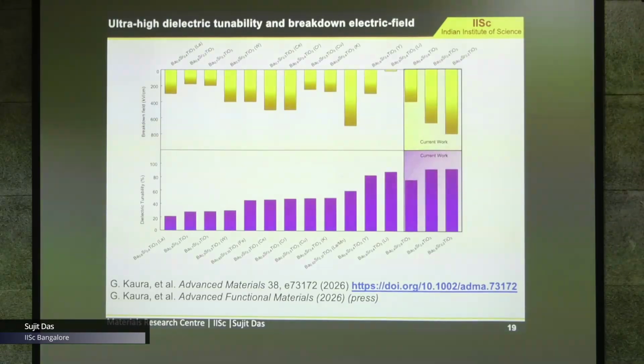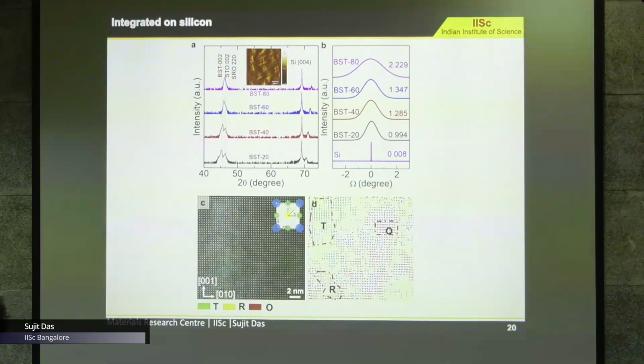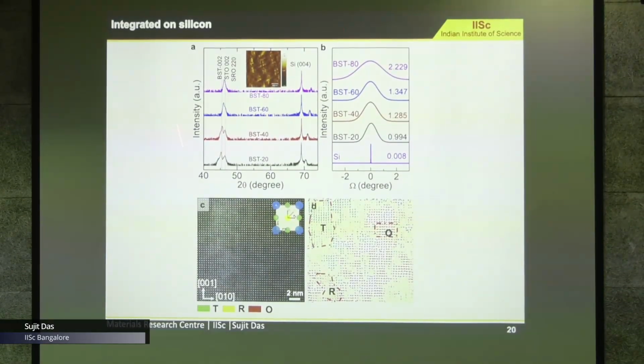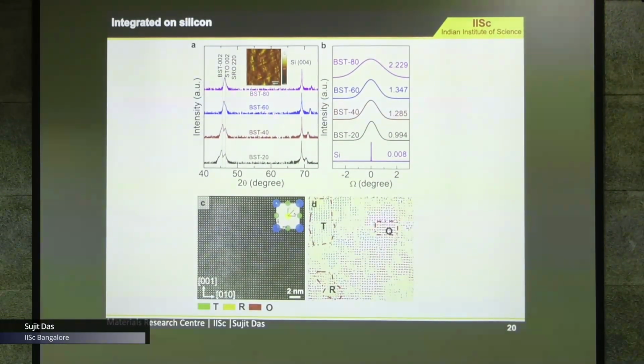Now the question is, can we integrate with silicon? We grew these materials on silicon as well. We take STO-coated silicon and grow these materials, and we can see again the phase is single crystalline and the surface is pretty smooth. The full width at half maximum from the rocking curve is okay, not so bad.